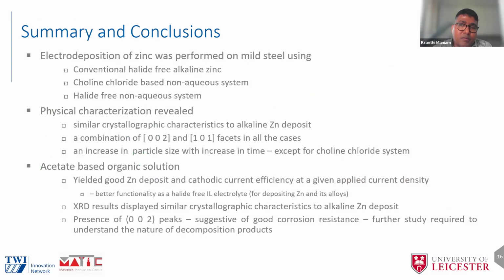So I would like to summarize. What we have done is to understand the choice of depositions. I tried to compare between 3 different systems. 2 were conventionally known, 1 is new, and I figured out that the halide-free non-aqueous organic solutions perform better, and they could get similar crystallographic directions. And also you can see that in terms of efficiencies, they could yield a better zinc deposit, and also better cathodic current efficiency for a given current density, which shows that it has a better capability, and it can function better in delivering the properties that are intended for corrosion protection.